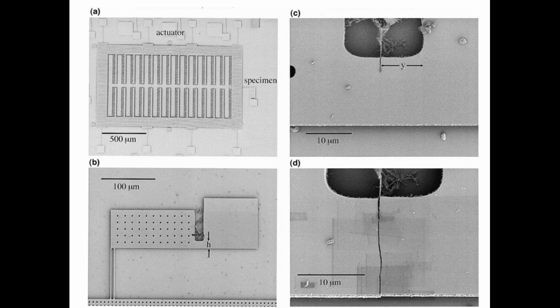So a digital twin of the experiment. Essentially, yes. And using this model, they could input the measured displacement at fracture and calculate the forces and stresses within the specimen right at the crack tip. This allowed them to determine the critical stress intensity factor, K_IC, the fracture toughness, based on that measured movement rather than the less reliable voltage. That's a really smart workaround. Using the displacement measurement fed into the FEA model.